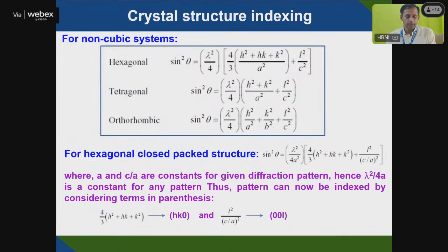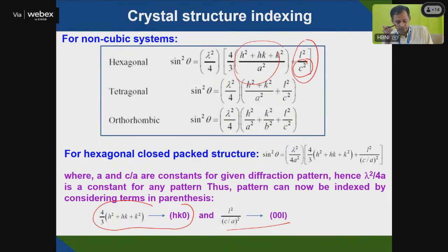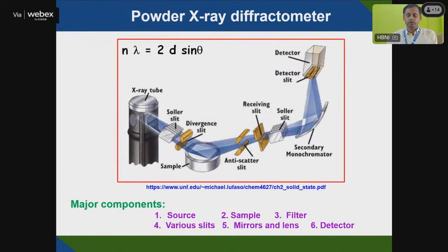Similarly, if you have a non-cubic system, like the hexagonal system, a c axis will come. So 4 by 3 times (h square plus hk plus k square) by a square, and l square by c square will come. In the hexagonal system, a and c are constant, so you get 4 by 3 into h square plus hk plus k square by a square for the hk0 reflections, and l square by c square for the 00l reflections. Accordingly you can find out what the crystal structure is. Similarly, for tetragonal and orthorhombic, you can identify their crystal structure by using this method.